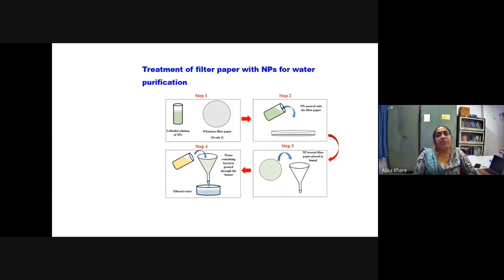What was done is that a filter paper was taken, and the colloidal solution containing the silver nanoparticle - we have demonstrated both for copper and silver - was poured onto it, and then it was dried. Then, using the filtration technique we learned from school age, it was placed into the funnel folded fourfold, and the contaminated water was allowed to pass through it, and we tested the filtered water.